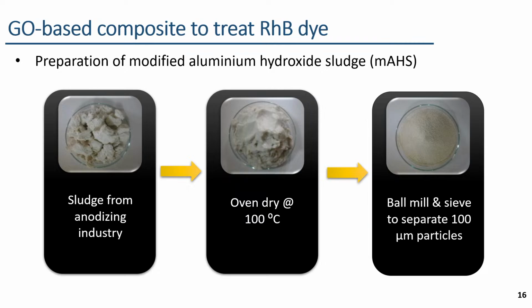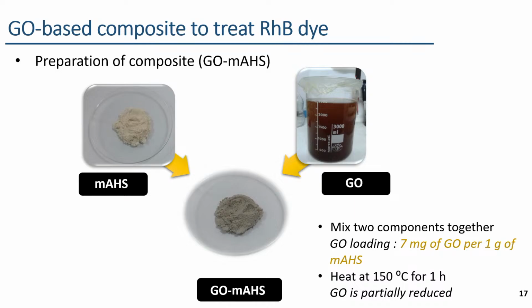In the preparation of this GO-based composite, first the aluminum hydroxide sludge was modified into modified aluminum hydroxide sludge. This aluminum waste sludge, which is discharged from the anodizing industry, is dried, ball milled and sieved to obtain modified aluminum hydroxide sludge with finer particles. After that, it is mixed with a small amount of graphene oxide to obtain the GO-based composite. After the mixing, this paste was partially reduced at 150 Celsius to obtain the composite with